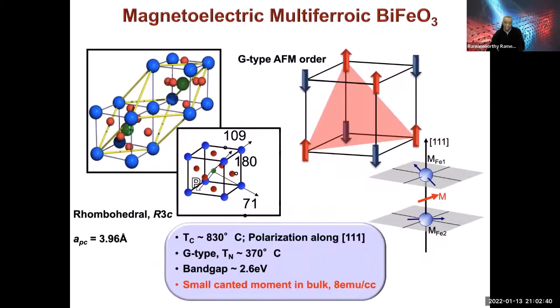Okay. For the next 10 minutes or so, we're going to focus on bismuth ferrite. This has really been heavily studied, and you'll see why in a second. It's got the perovskite structure that you see on the top left. It has a very high TC. And indeed, in early days, the big argument was we published a paper where we said that the polarization is about 90 microcoulombs per centimeter squared, perhaps the highest polarization. A lot of people in the community said, that's crazy. And indeed, it turned out to be okay.